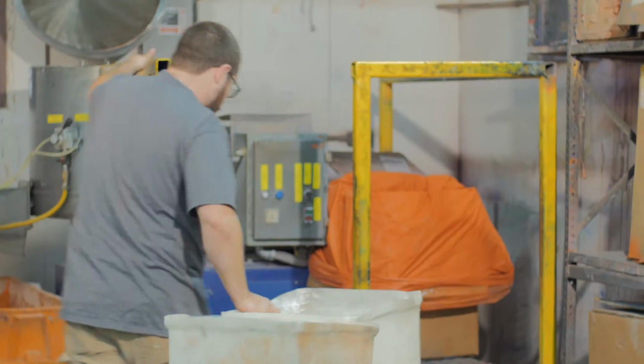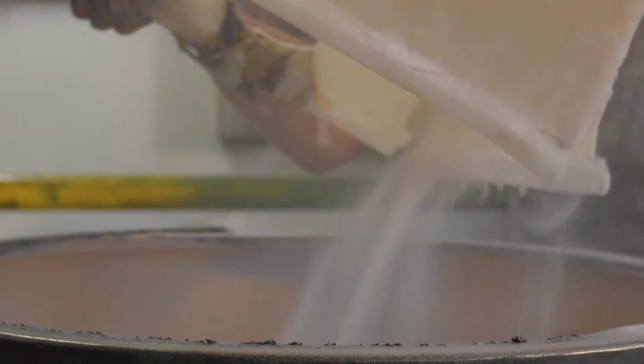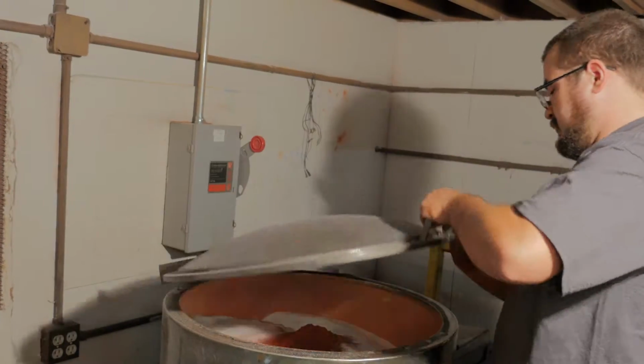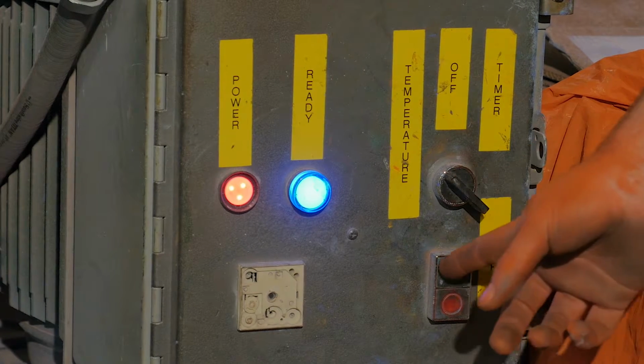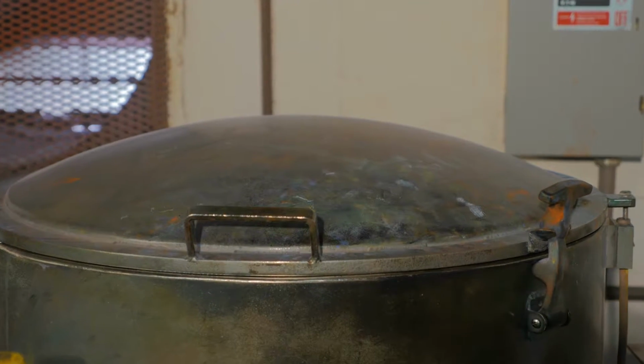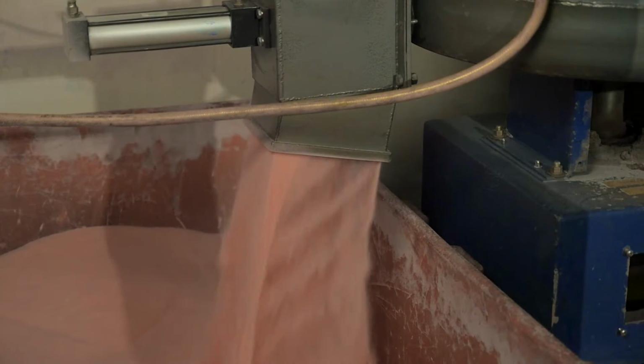Preparing the raw plastic for molding involves several important steps. First, the plastic is vigorously mixed to eliminate any clumps that might keep melted plastic from flowing into small spaces in the mold. The high-intensity mixer also preheats the resin, reducing the moisture level to the required range. Mixing also improves resin flow characteristics, ensuring a smooth exterior surface on the pallets and consistent pallet wall thickness. After a thorough mixing, the raw plastic resin is ready to be molded.